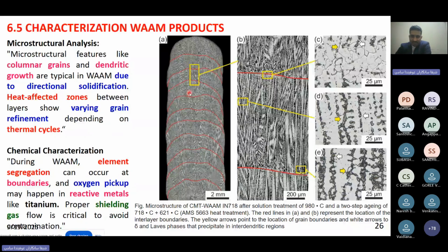You can see the pictures, SEM pictures. This is layer 1. The red line indicates the interface between the two layers, the interface between two layers. And you can see a columnar grain structure is getting formed. Still, if you have the magnification, you can see some metal carbides, some elements segregated, which are inside the grain. They call these interdendritic regions. So these are the microstructures usually formed in the case of WAAM processes. That's the point.